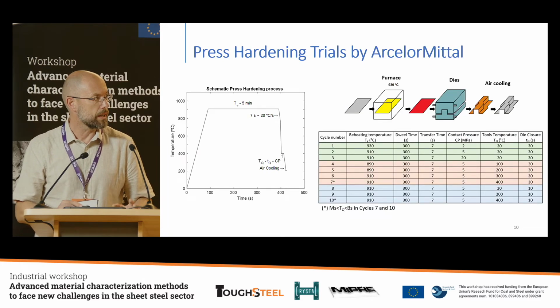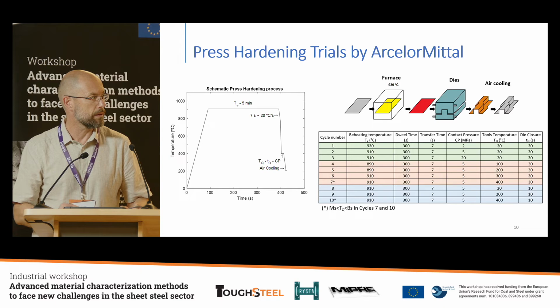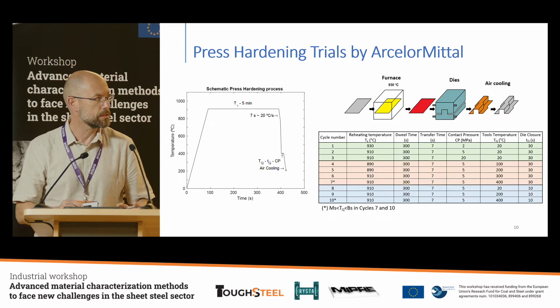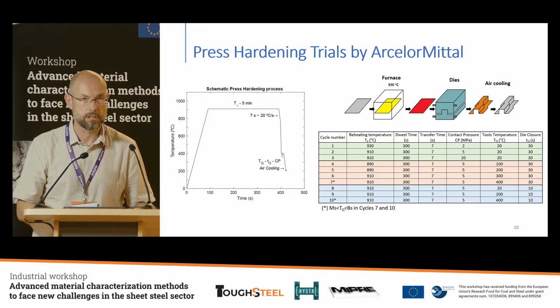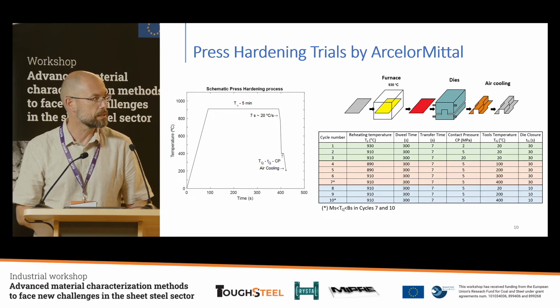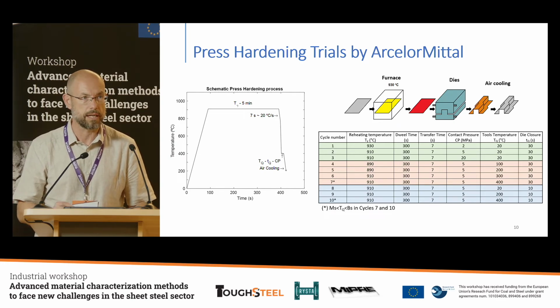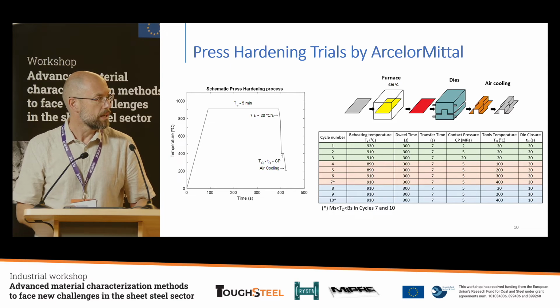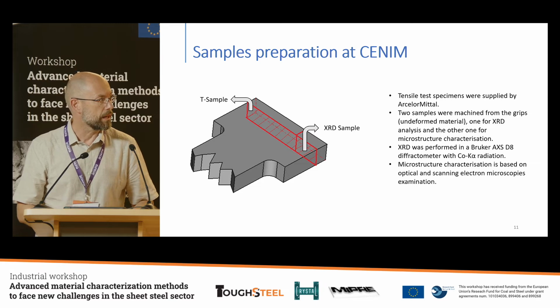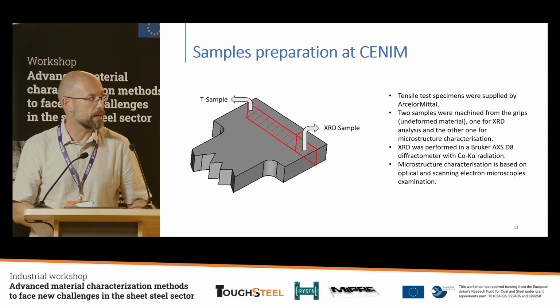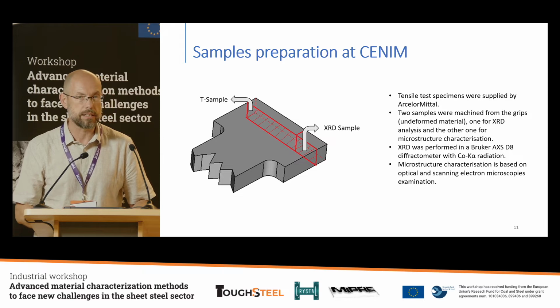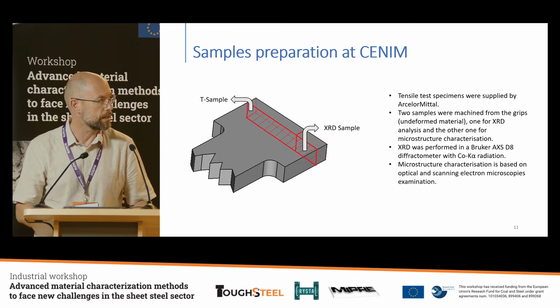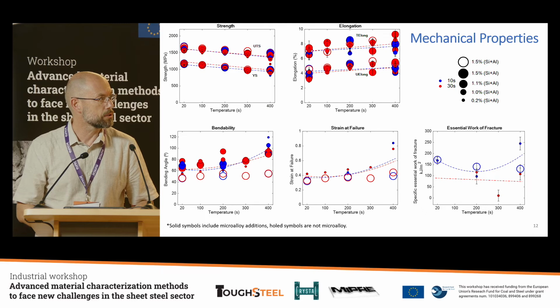And we were taking into account the different parameters that we have in press hardening: the reheating temperature, the contact pressure during the process, the tools temperature, and the die closure time. And we selected 10 different conditions, combining the 4 different parameters that we are going to analyze. We explain here where the different tensile test samples produced after the processing were obtained from. And we got some results here.